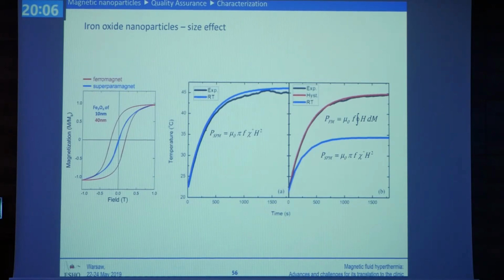But if you use that, and your nanoparticles are actually ferromagnetic nanoparticles, they are 40 nanometers, you lag behind in the energy that is transferred to your sample, and then you have to use the ferromagnetic power calculation to have a matching between your numerics and your experiment.